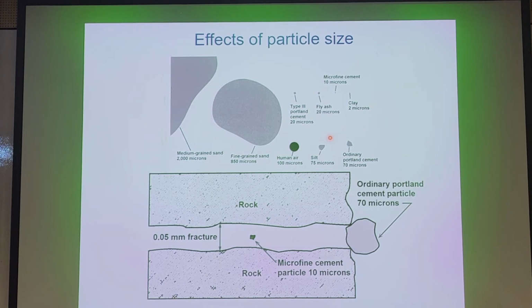Underneath, you can also see other types of geomaterial. We have silt, and then we have ordinary Portland cement, which is quite large, 70 microns. Now, if you want to fill in fissures in the ground, at the bottom is an example of a fissure or crack in the ground between 2 masses of rock. The fracture is about 0.05 millimeters. If you use microfine cement, you'll be able to permeate into this fissure, because microfine cement is 10 microns. But if you use ordinary Portland cement, you're not going to be able to permeate into your fissures.